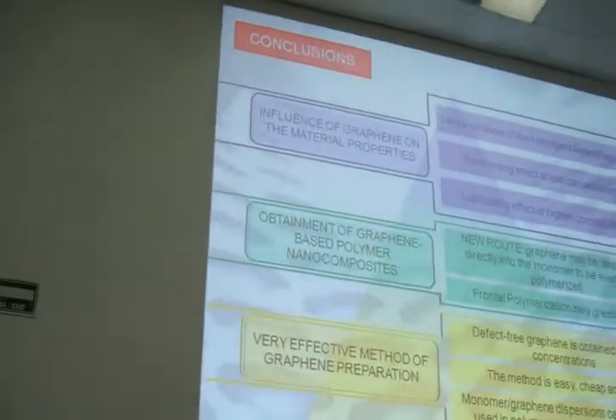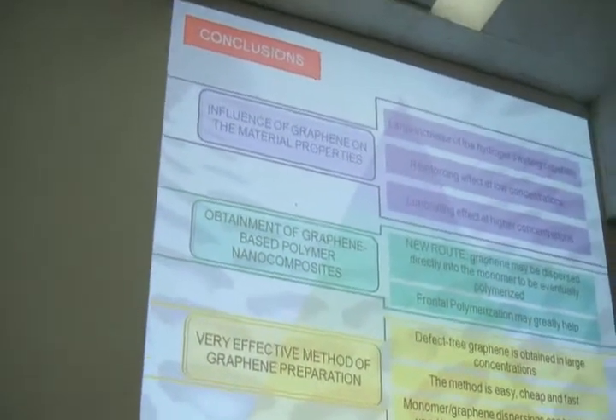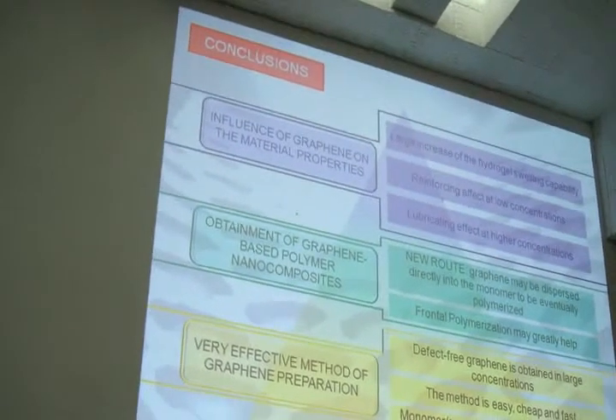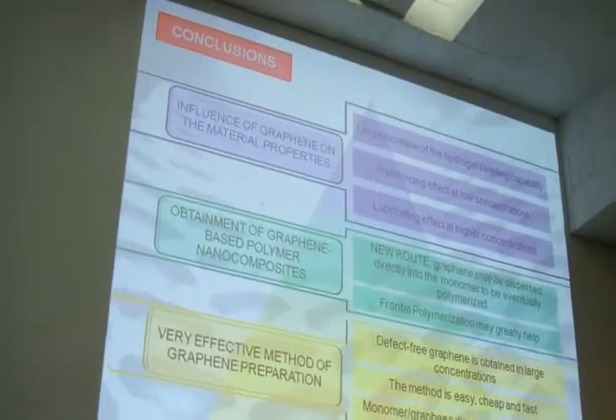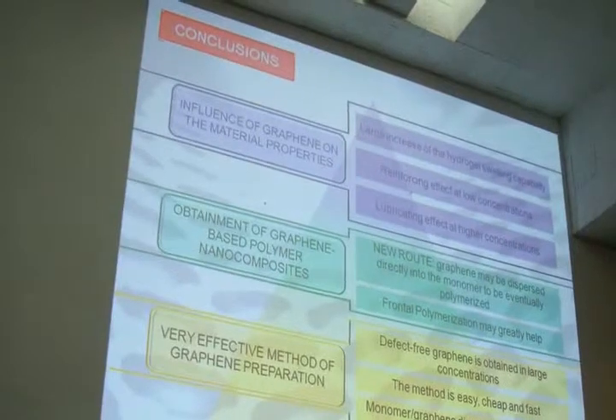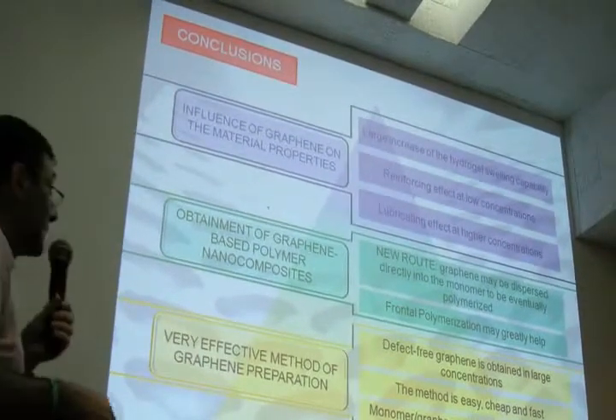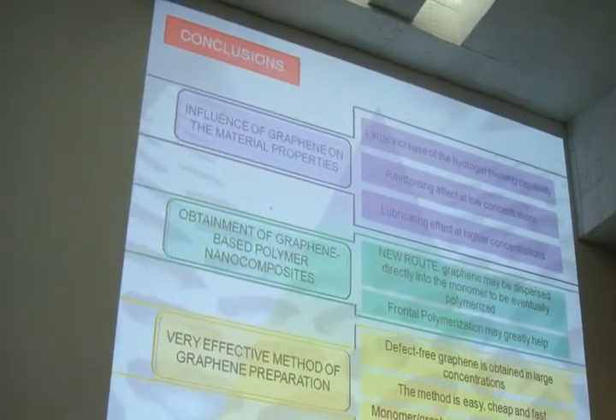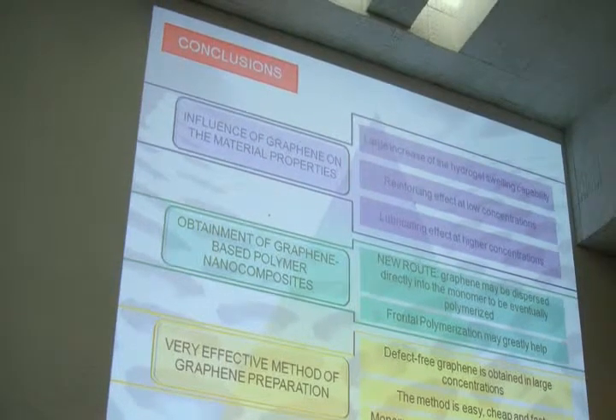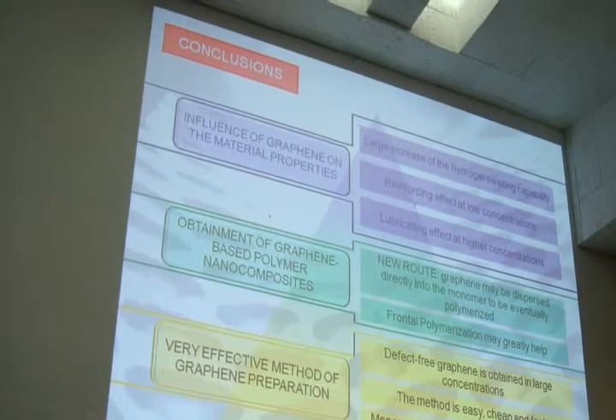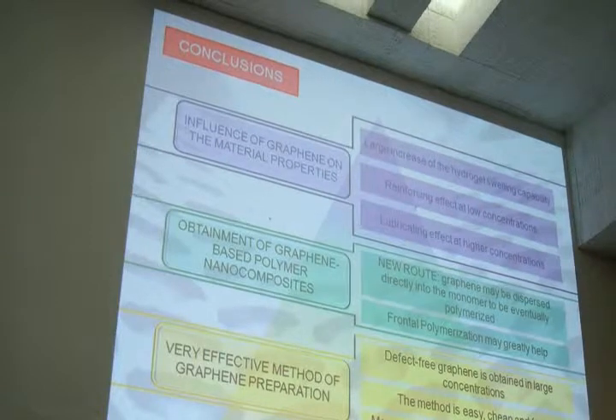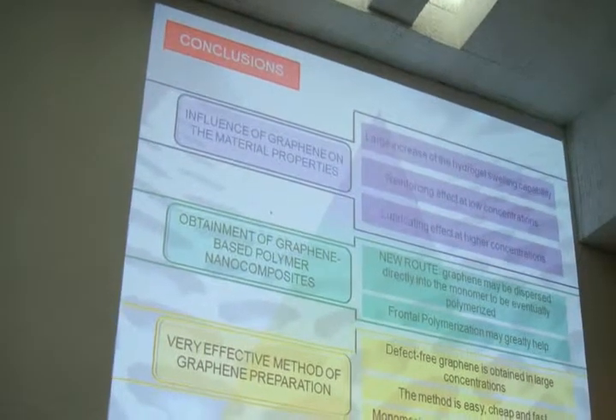What we observed in these two cases, but it's something quite general in all other systems we have studied, is a large increase in the hydrogel swelling capability, a reinforcing effect up to a threshold value, but a worsening effect after that threshold value. That's all. Thank you very much.